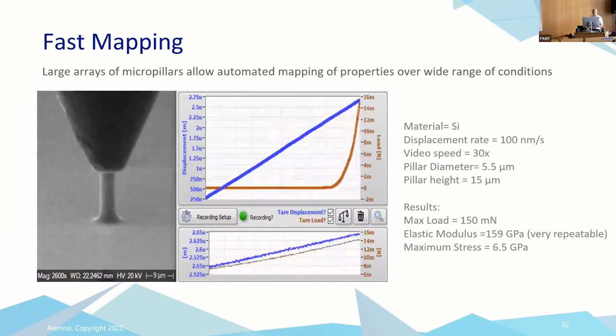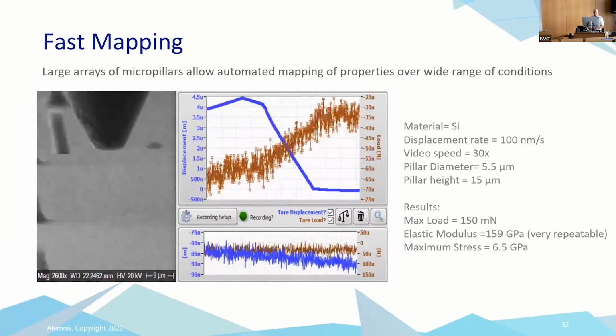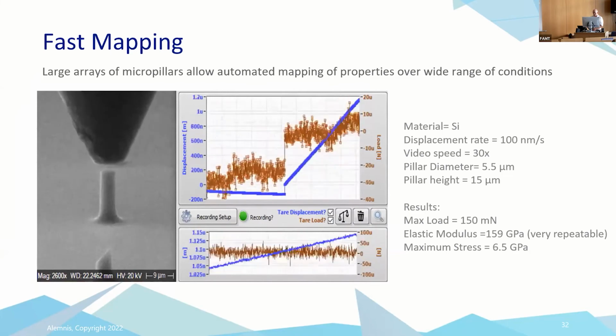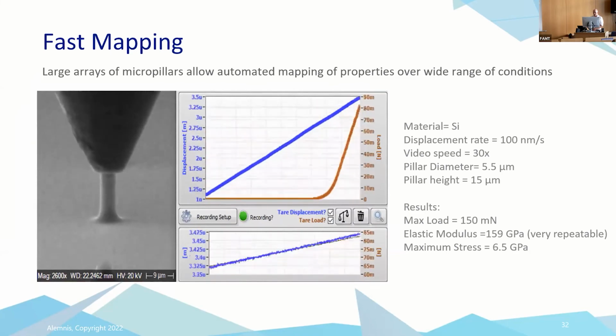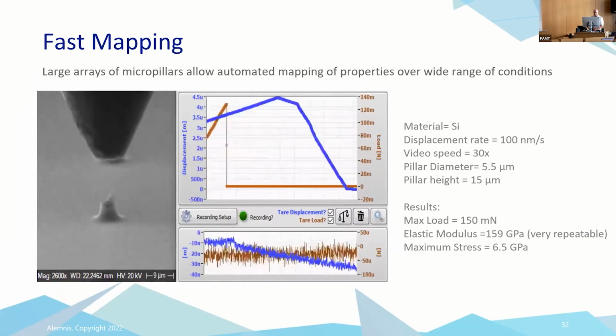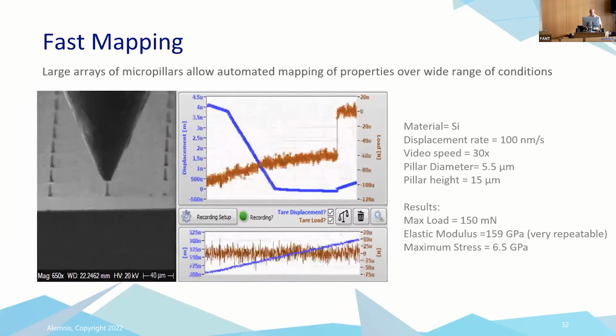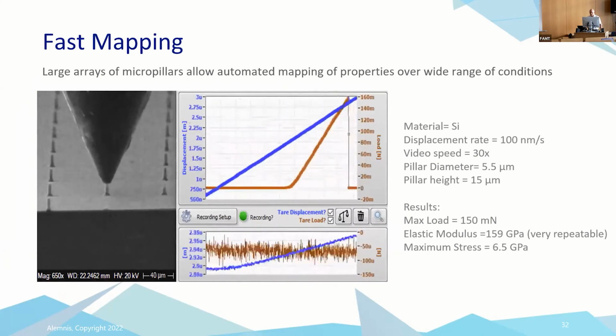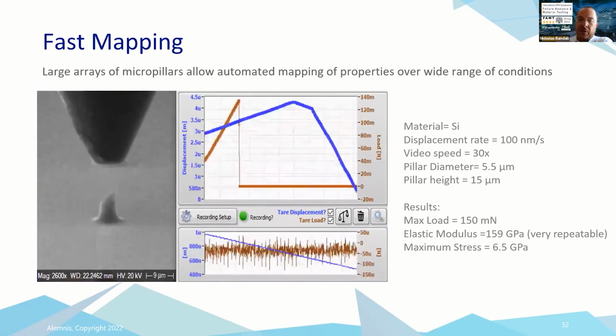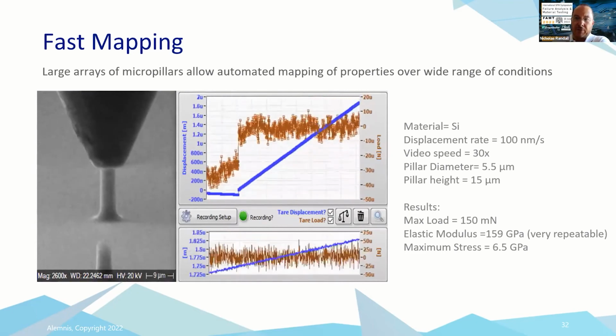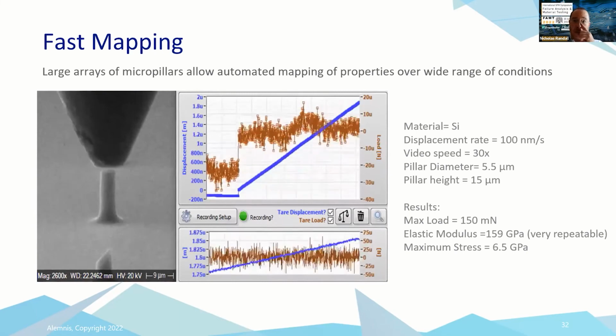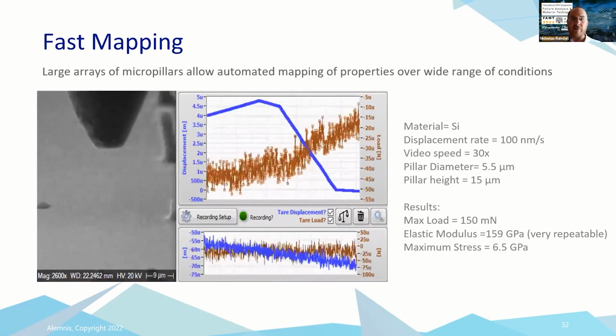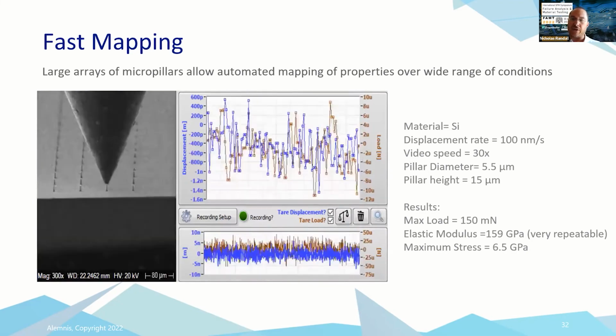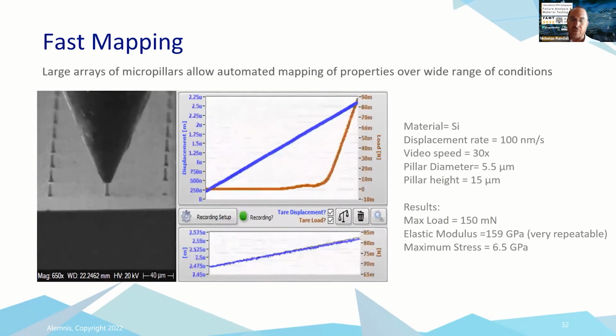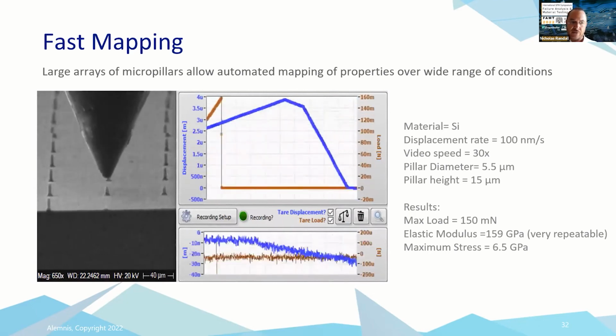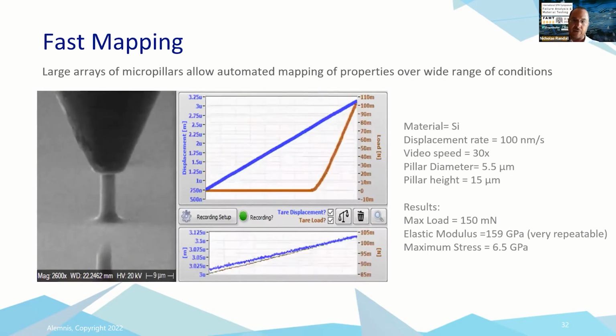Okay. We have a question in the back here. Fraunhofer, IASB. I'm very much excited about the nano indentation inside the SEM, or in the focused ion beam. What temperature ranges can you do in the chamber? Is it the same as the external one? It's actually higher. We're helped in the SEM because we're doing high temperature in a vacuum, so we don't need to worry about heat loss by convection. We only have to worry about radiation loss. So we have modules going up to 1,000 degrees in situ, and down to about minus 150 using liquid nitrogen.